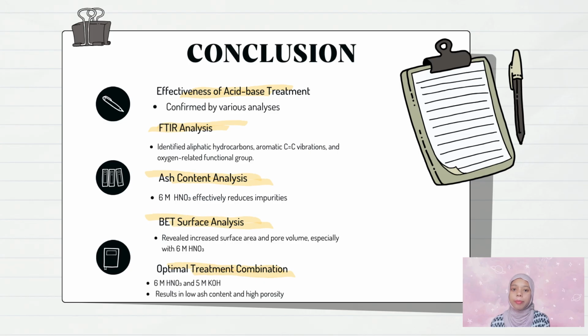To wrap up, our study demonstrates the significant impact of acid-based treatment on the quality of RCB derived from waste tires. Here are the key takeaways. Firstly, reduction of impurities. The treatment, particularly with 6 molar HNO3, effectively reduces the ash content in RCB. This purification process removes inorganic contaminants, bringing the quality of RCB closer to the VCB.